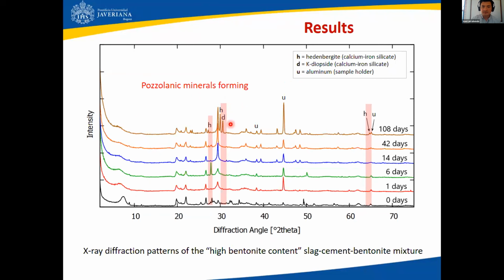There are very sharp peaks at 3 months, and perhaps there would be sharper peaks if this study had been performed over a longer period. However, the minerals that we confirm are different. They are distinct from those in the field representative sample. We have, I hope to pronounce this well, hedenbergite and K-diopside, both of them calcium iron silicate. And those are pozzolanic products, and they have been reported in the past as pozzolanic products as well.